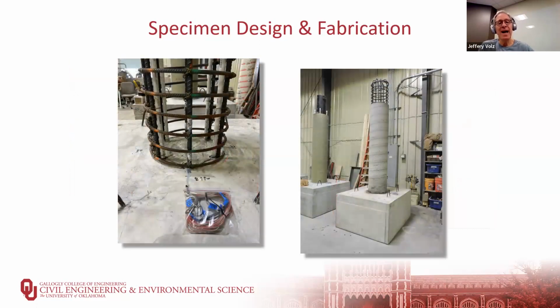We also designed and constructed a reinforced concrete column with a nominal 18 inch diameter. The reason we wanted to do that, even though these columns have been tested to death, is because we wanted to make sure that our testing system and our loading protocol gave us the right kind of response before we put in these new columns, our HCFCS columns. So it's an 18 inch nominal diameter using a sonotube for the form. There are 8 number 6 bars for longitudinal reinforcement, a ratio of about 1.3%.